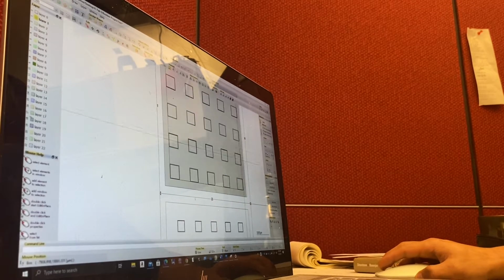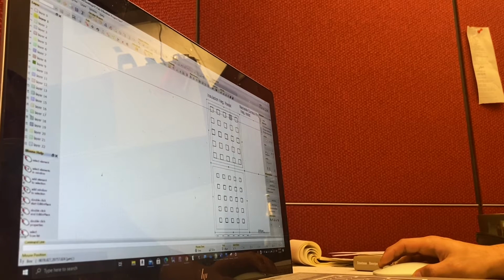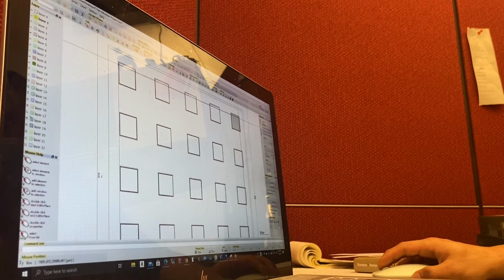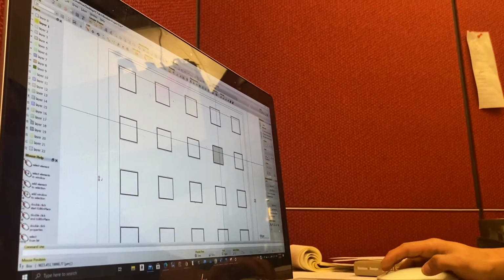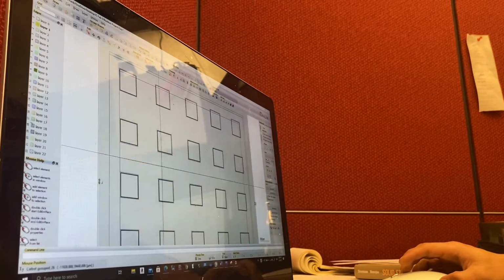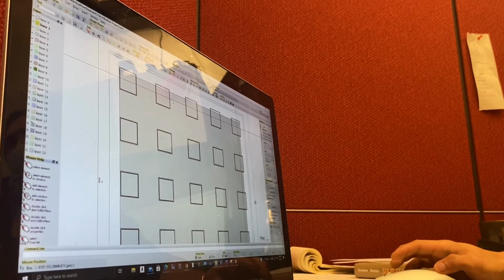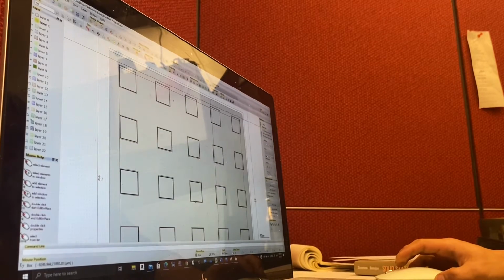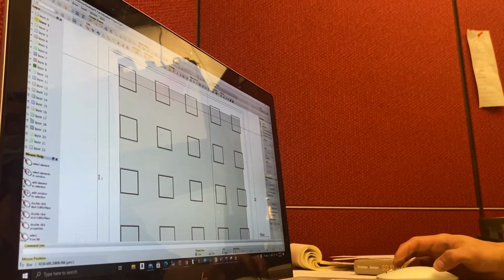Okay. So for example, on these top ones here, and this one is the worst because it has the overlap here. Now you may measure your device, you may measure this one and be like, oh, it's good. Maybe all these perform very similar, and then you see this one performs really bad for some reason. And this one performs bad, but not as bad, and you wonder why. The reason is because part of it's being covered by gold, and it's not absorbing as much light.